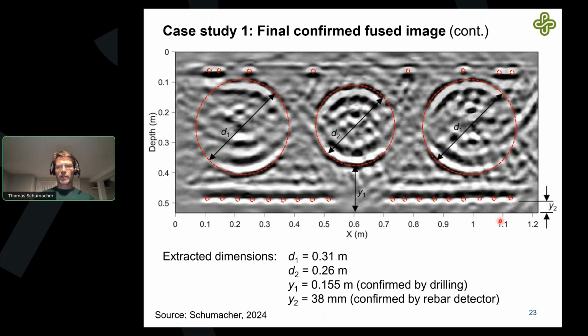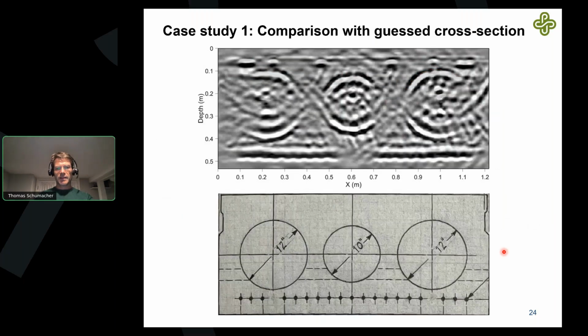So this has turned out to be very useful. This is what we anticipated. This is what we had, and it turns out they were very close, except for the cover here of the rebar, of the pre-stressing strands. That was a little bit different. But now we knew exactly what to work with.